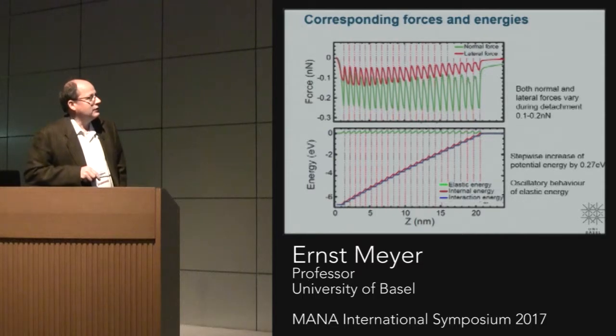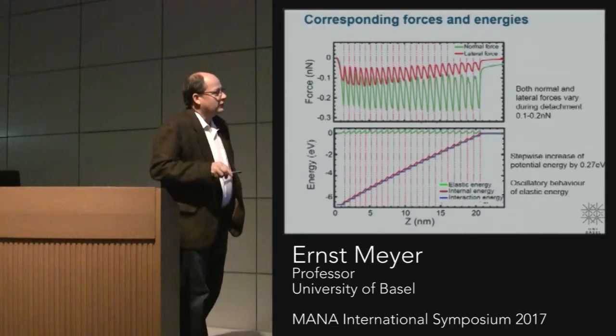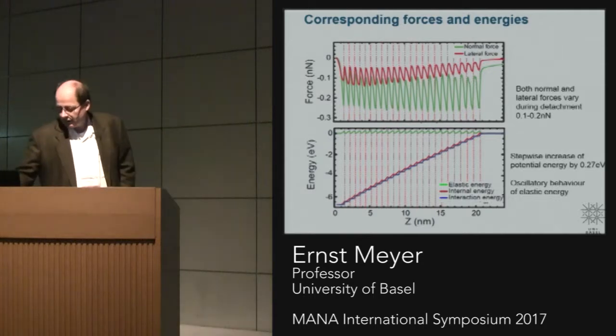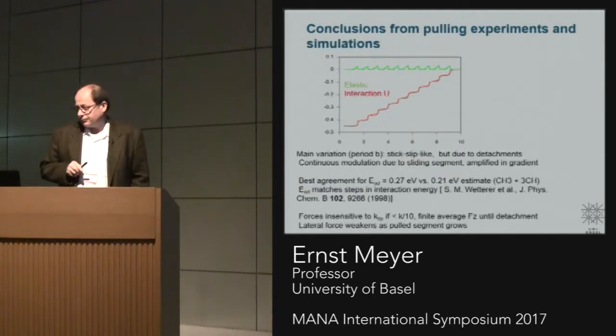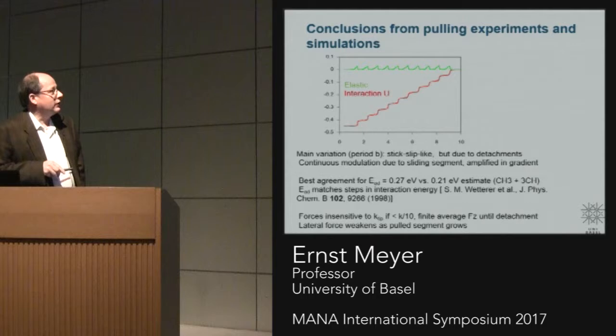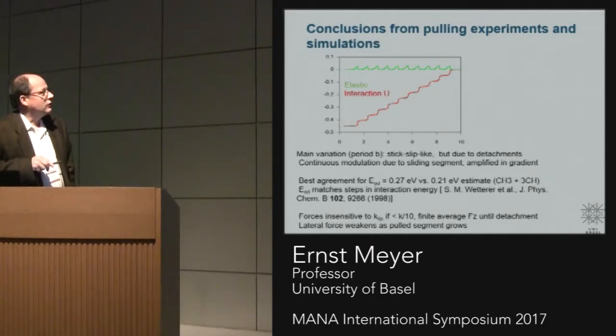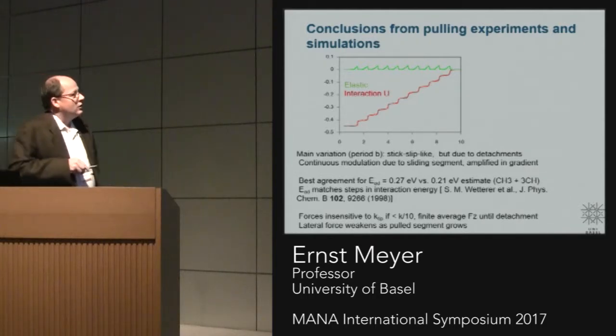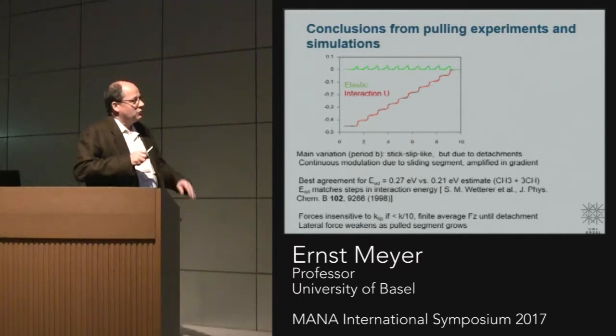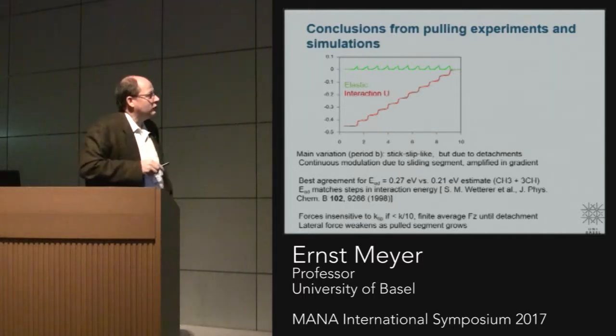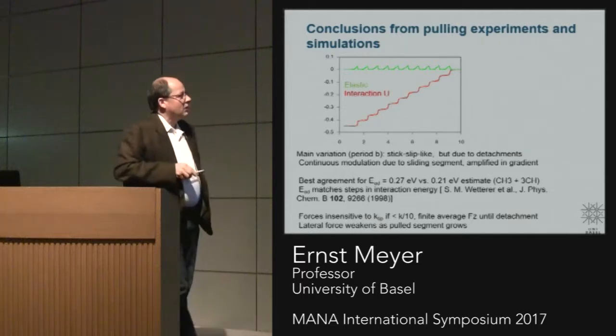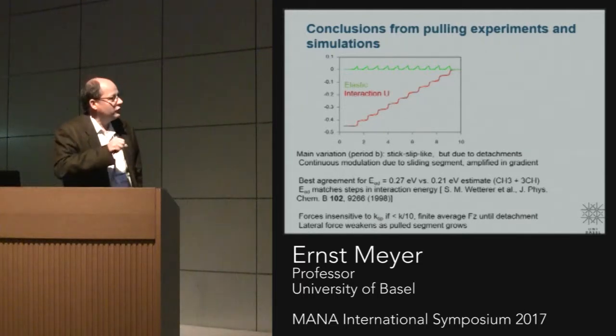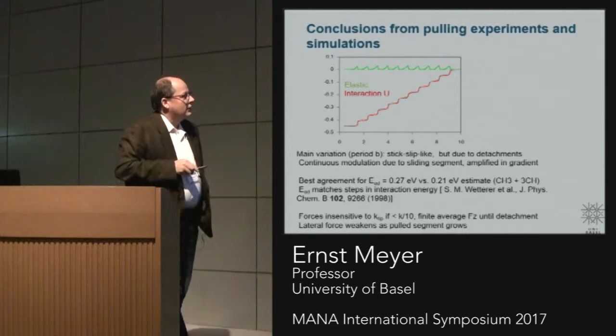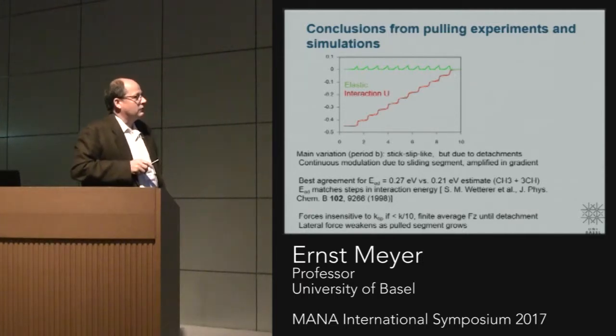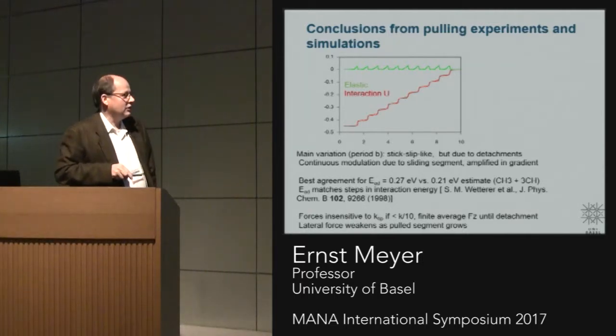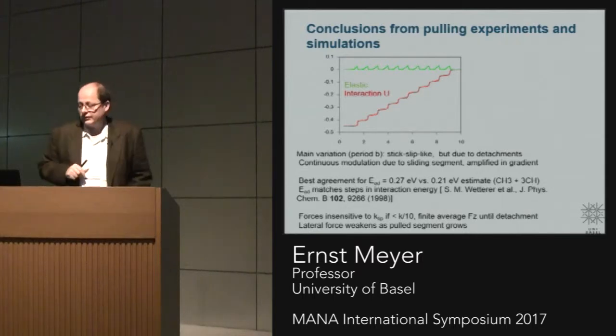And in the energy, it's also quite clear. You have this stepwise increase of the potential energy. It's around 0.27 electron volts. So that's shown here again a bit more detailed. You can also see the elastic deformation and so on. This 0.27 electron volt, that's more or less the detachment of one of the subunits, and you can compare it with, I mean, it's basically a methyl group which detaches from the gold surface, and that's quite consistent with some other theoretical calculations.